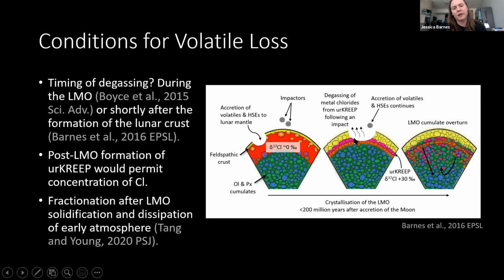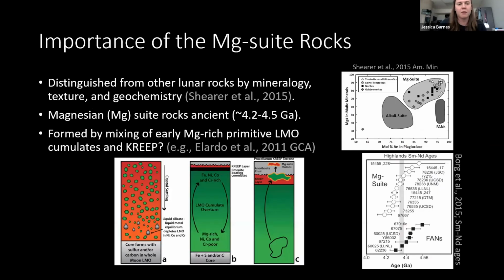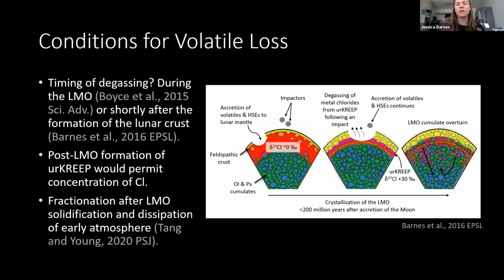And so we went a step further to say that not only would impacts have been important, but potentially large crust-breaching impacts could have facilitated the loss of the lighter chlorine isotope to space, maybe depositing on the surrounding cold crust and fractionating the remaining urKREEP that was left behind. So that was kind of the story in 2016, and we had a follow-up paper in 2019 that corroborated that. But one thing we were always met with was, well, what if the samples where we're recording these high values are just a crustal process that's happening and it's not anything to do with urKREEP?